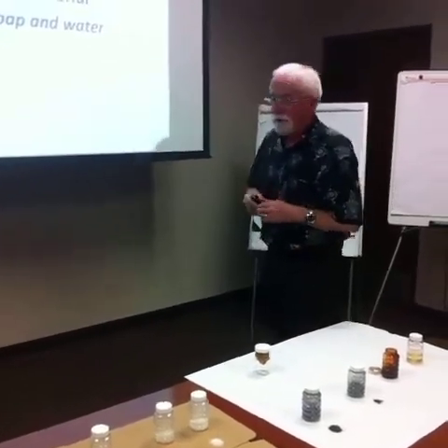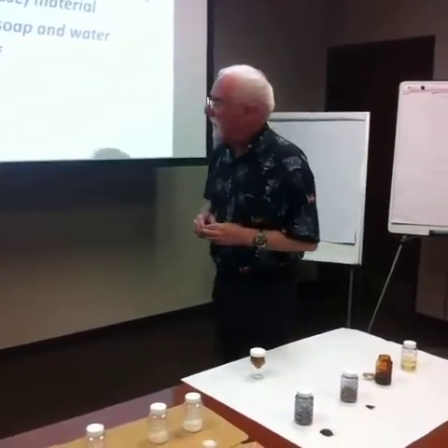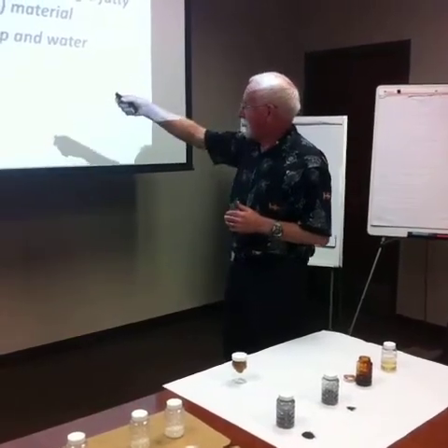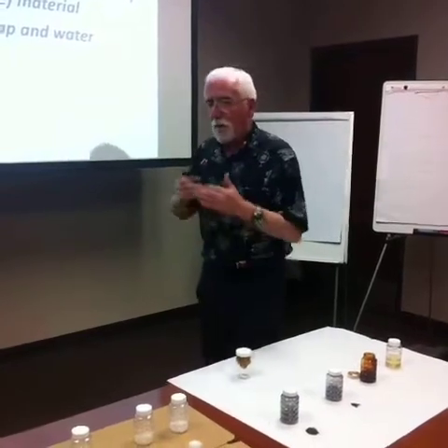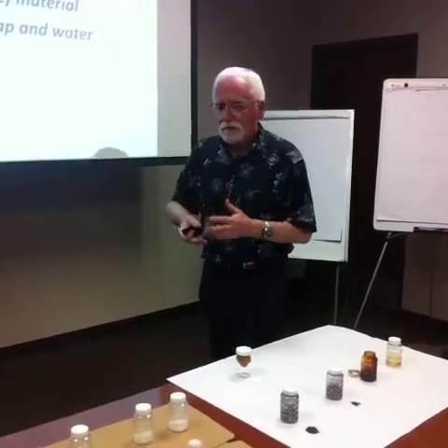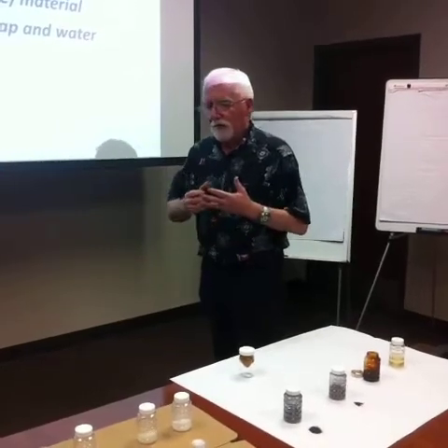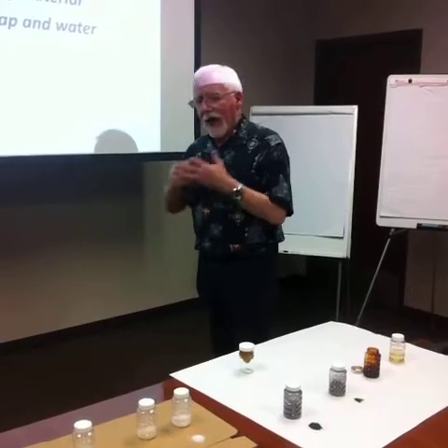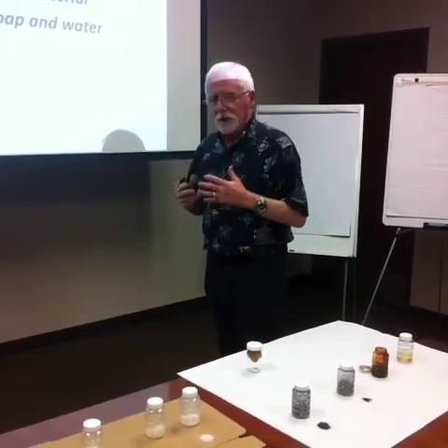The primary worldwide thickener for grease is lithium soap, and it's made by reacting a fatty acid with an alkaline or a base material, and the end result is a soap and water. Then we continue to heat the grease until the water is evaporated. That gives us our soap. We then move that from the soap mixer over to the grease mixer. We add the oil, we add the additives, we homogenize it, smooth it out, and package it, well, screen it,